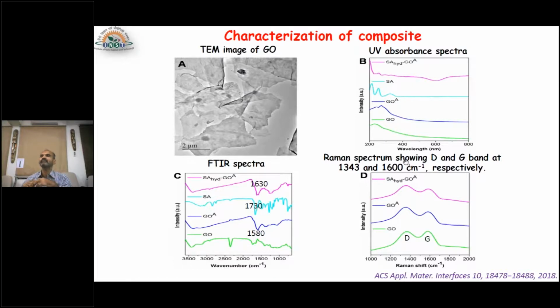Say for example, carbon characterization will be very clear when it is done with Raman spectrum. And the graphene oxide, as you can see, when it is run for this Raman spectrum, you will find this 1300 and 1600 peaks as like this. The 1300 is the defect peak and the 1600 is the graphitic peak. As and when the conjugation is increased, because of the more and more conjugation that you are giving to the surface, the defects increase.